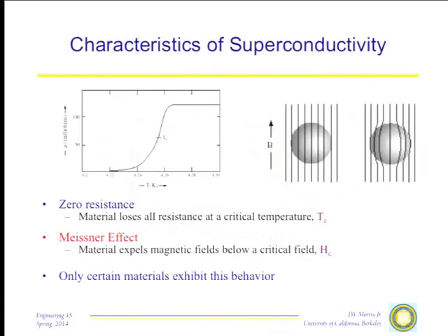There are two properties of a superconductor, really, and they're tied in together. Superconductors have 0 resistance, strictly 0 resistance, not approximately 0. The resistance of a superconductor has been measured with great precision and is lower than any number that one can measure. They also exhibit what's called the Meissner effect, that is, that they exclude magnetic fields, and that can also be tied in with the 0 resistance. Because if we put a material in a magnetic field, the diamagnetic behavior says that you will introduce a circulating current that opposes the field. If there's no resistance, that circulating current can become as big as it needs to be to exclude the field, and that's what happens. That's the Meissner effect.